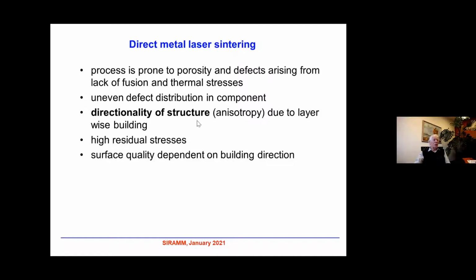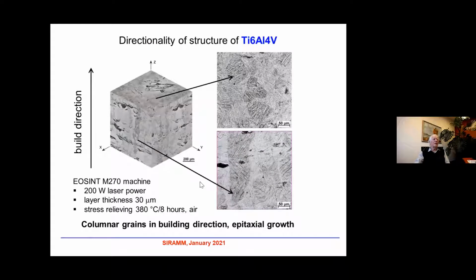So now to directionality of structure, anisotropy. Again, the case of Ti-6Al-4V alloy. This direction is the build direction of the material. The machine used was an EOSINT M270 machine. The laser power was set to 200 watts, layer thickness 30 microns, and the material was stress relieved at 380 centigrade for 8 hours in air. The microstructure consists of columnar grains in the building direction, and we can see here epitaxial growth. On this plane, which is perpendicular to the build direction, you can see cross-sections through these columns. So the microstructure is different in different orientations.